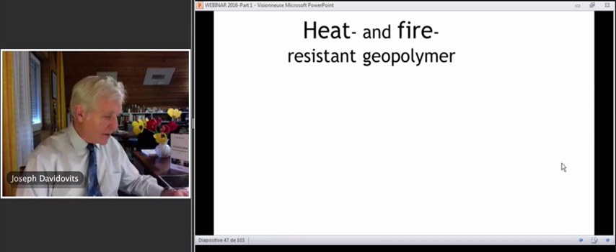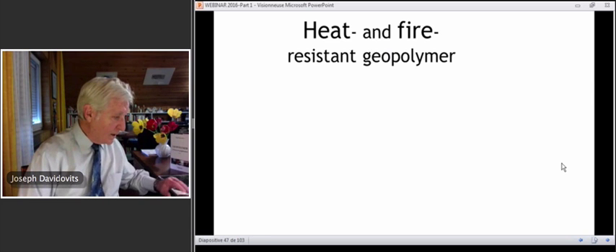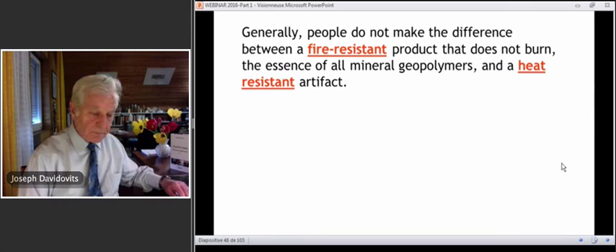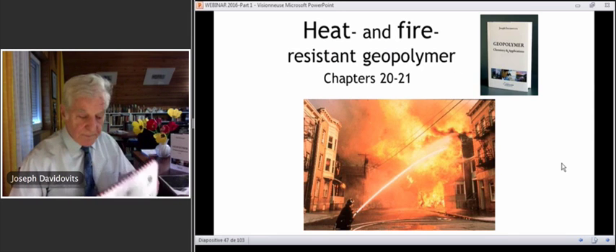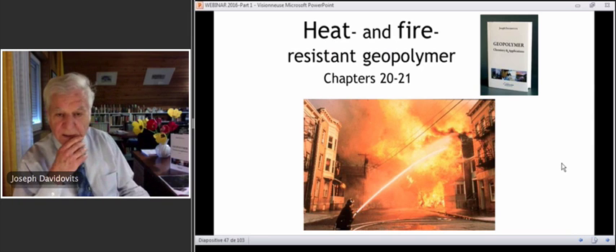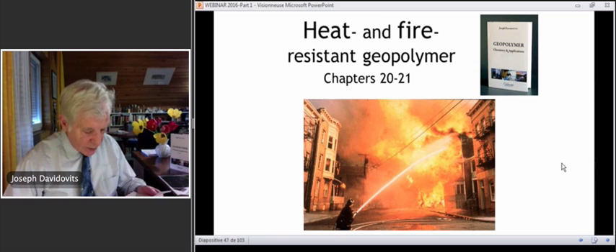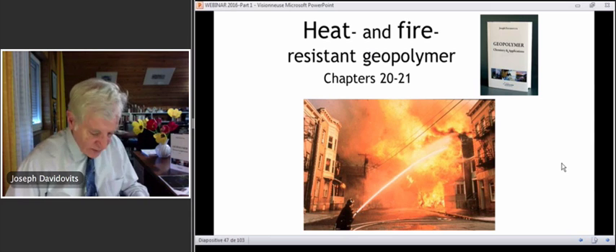Heat and fire resistant geopolymer. Pardon, too early. I received an email, I read it. "Geopolymer material with expanded glass as filler material. I want heat resistance up to 1200 degrees C with expanded glass as filler material." My answer to this email was, this is impossible because expanded glass is melting. Are you sure you want heat resistance and not fire resistance? He answered, yes, it is fire resistance that I want. That has to be tested up to 1200 degrees C.